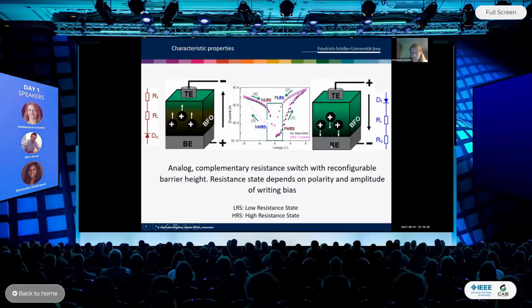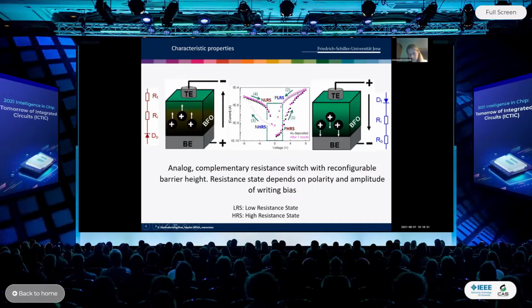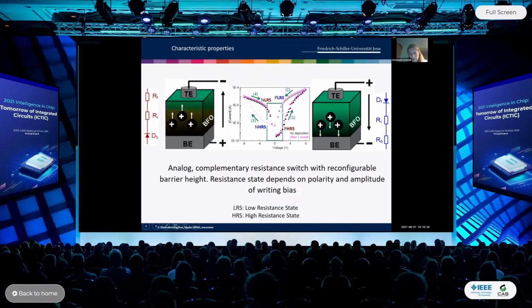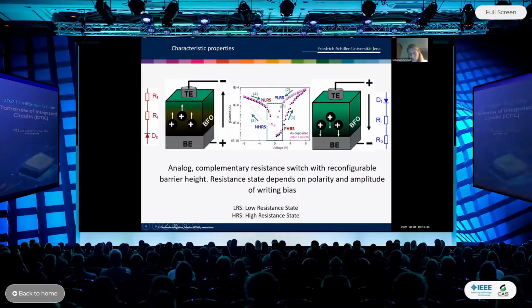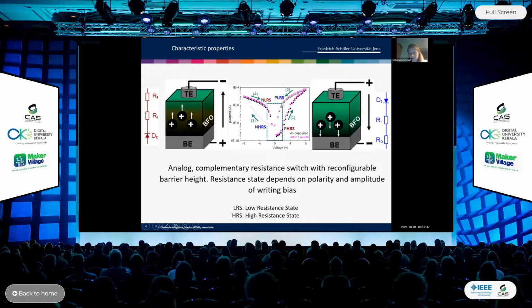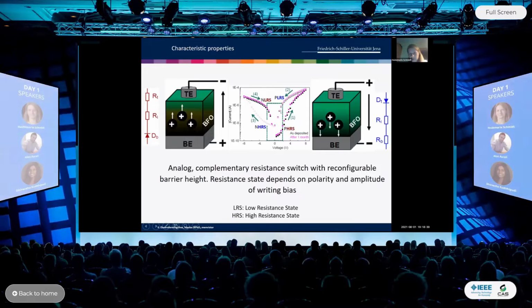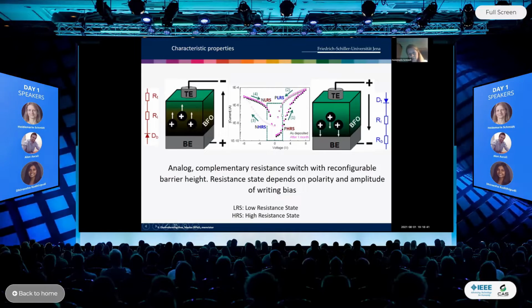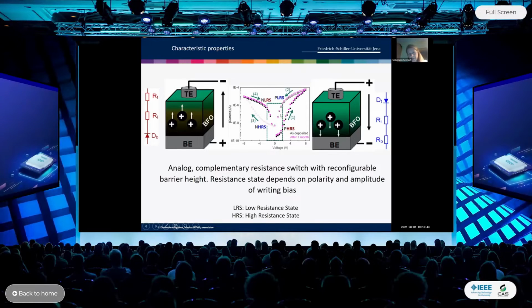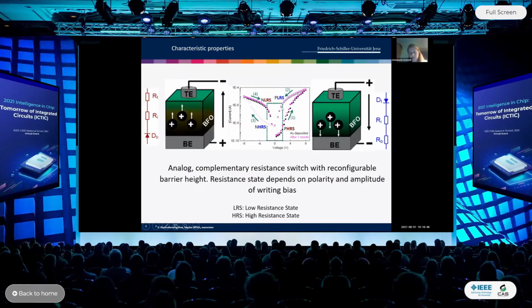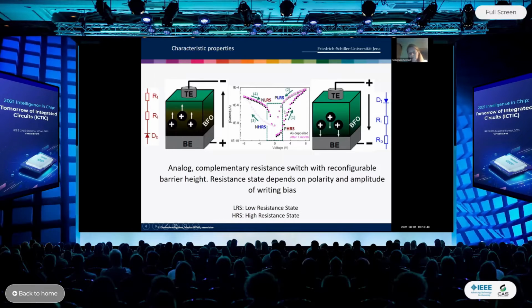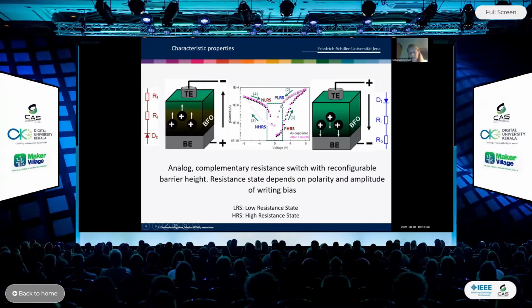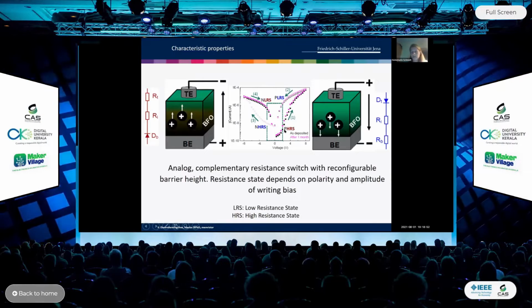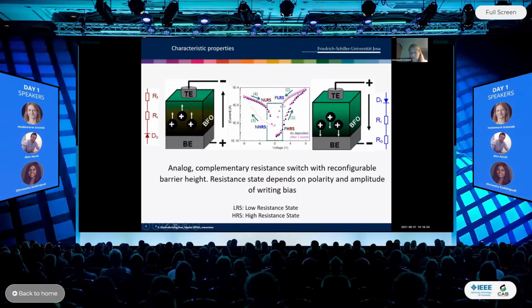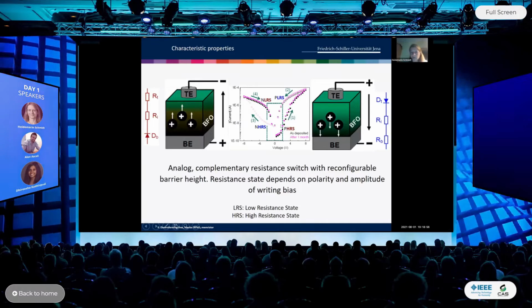And it's not just a Boolean function, because the amplitude of the writing bias determines whether we reach the complete maximum value of the low resistance state or whether we have intermediate values. And because the system can take on intermediate values of the barrier height, and with that of the readout current, we have the possibility not only to realize and emulate the Boolean logics, but also the analog logic, which is called fuzzy logic.